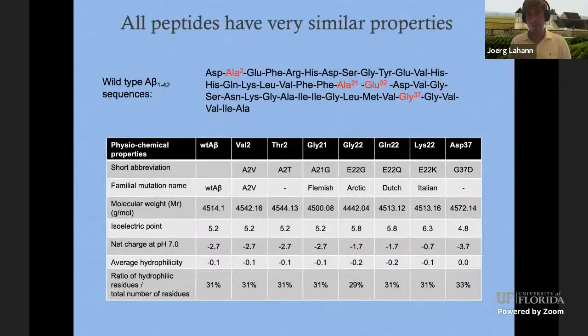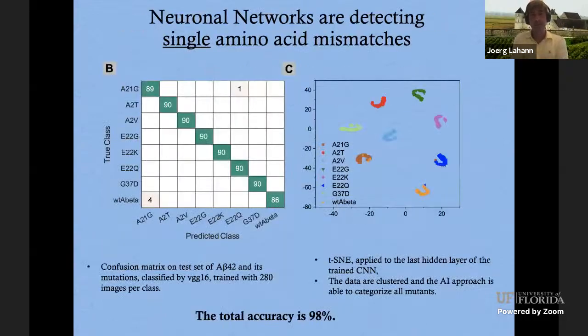First of all, let me show you the physical properties. So molecular weights are essentially identical. Isoelectric points are very similar, except maybe the lysine 22. The hydrophobicity is very similar. So it's very hard to make a lot of sense out of this just from a physical analysis. So when we run it through our neural network, first of all, they cluster very nicely in our t-SNE plot, so they're very different from each other. I think that's what this suggests here.